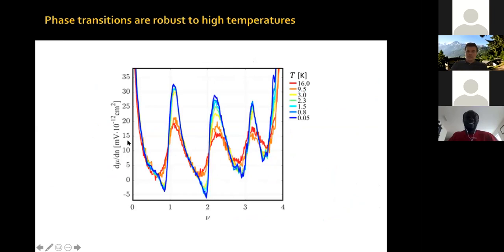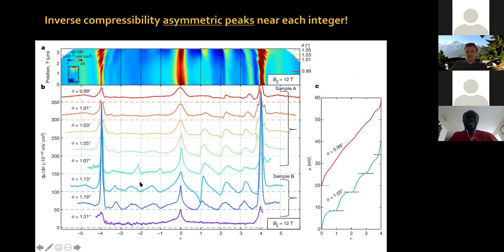So what I'm trying to tell you here is that this response, which is generic within the magic angle range, in a range of angles around the magic angle, from 1.1 plus minus 0.1 degree kind of, okay, we see this phenomenology of these asymmetric peaks. In fact, here I forgot to tell you, you can see this trace at 1.31 degrees has no features whatsoever, only the Dirac and the band insulator peaks. There are no sawtooth peaks here, okay? Because 1.31 degrees is beyond the magic angle range. For 0.99 degrees, you see a little bit here, so there's still a little bit there. As I mentioned before, we've seen superconductivity down to 0.95 degrees, so the magic angle range extends from about 0.95 to 1.25 degrees, something like that. You go outside that and you see no features, okay?